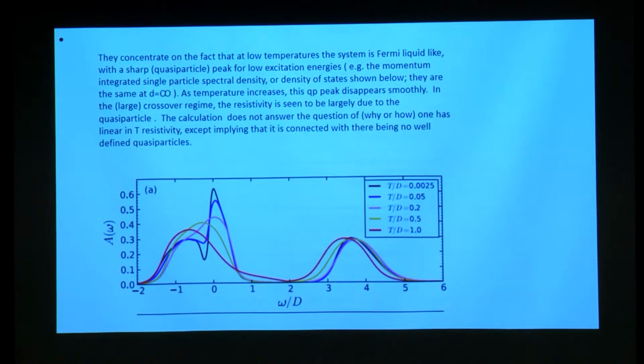And this peak becomes more and more peaky as the temperature decreases. So their focus was mainly on how this happens. That is, how as you reduce the temperature, the resistivity is dominated by the quasi-particle part of the single particle spectral function, and they showed that this does happen.